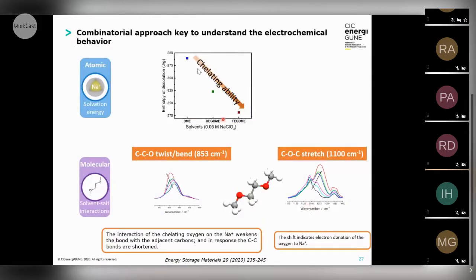In the case of the first one, atomic, we already know the enthalpy of the solution, that the chelating ability of these three solvents is going to increase as we increase the solvent chain length. In the case of the tetraglyme, we have five oxygens, and just one molecule of tetraglyme is able to solvate sodium by its five oxygens. That is going to be really highly bonded, and that's the reason when you go to high rate using tetraglyme, we are not able to cycle the battery.